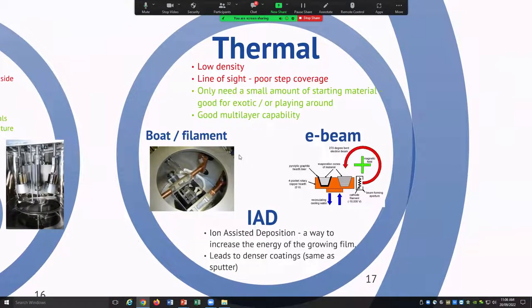Thermal evaporation, it's literally you're boiling the material. Think about boiling a kettle, that's what you're doing, instead of it being water, it's whatever material you've put into your boat, and you're just getting it up to its vapor pressure, and then it just sprays out everywhere. So it's typically a bit lower energy, so you end up with a lower density coating. Again, it's line of sight. Good thing about thermal evaporation is you don't need a lot of material to play around with. So if you're doing new coatings, new materials, it's a good way to do that sort of thing.